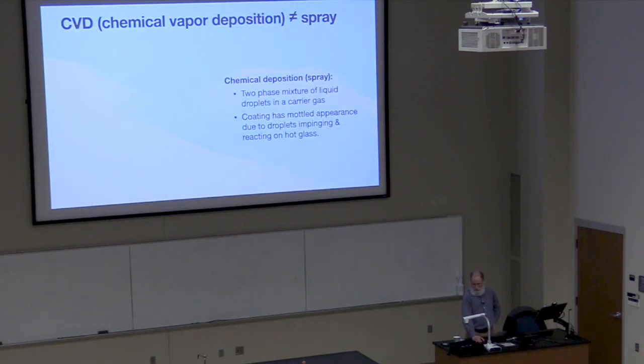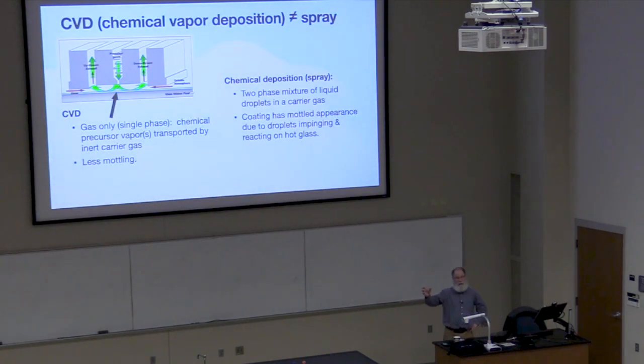The other thing about this process is that it's not a spray process. Think about a spray bottle at home: you pull the nozzle and you get little droplets. That was the early way glass was coated, or that was one way it was tried at least. The problem with those little droplets is it's two-phase. You have liquid and a gas, and when that hits the glass, you get a little mottled pattern. So this chemical vapor deposition means we choose chemicals that are a gas, not a liquid, and we carry them in a gas so that it's just a single phase. So we are able to control the color and the pattern much better.